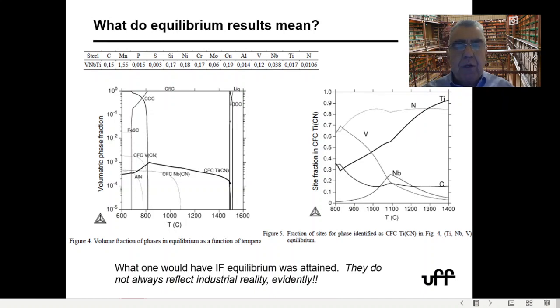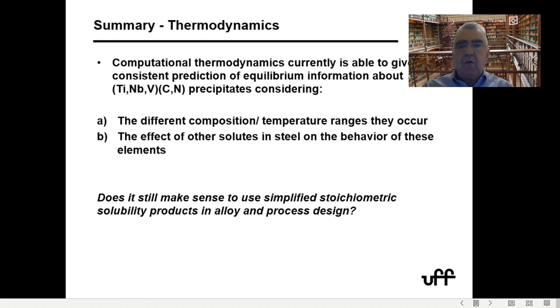And also, if you're looking at the thermodynamics, there's really no sense in introducing deviations that are kinetic on the solubility products. They should be done afterwards when you're doing the kinetic calculations with the proper thermodynamic data. So in summary, computational thermodynamics can now give you a very, very consistent prediction of equilibrium information of these carbonitrides of all the microalloying elements, considering not only the different compositions and temperatures in which they occur, which is already a big challenge because you have them occurring from relatively low temperatures in steels like vanadium nitride to very high temperatures for the titanium nitride.